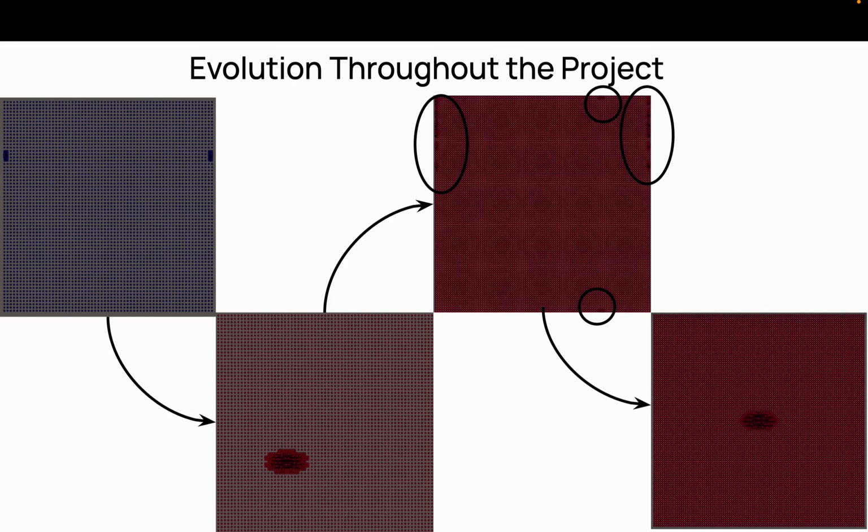At some point, when the precipitate was showing up in its hole though, it was round at the center and was showing up in random locations, as seen here in the second precipitate. After implementing the elastic energy properly though, this problem went away because the elastic energy implemented a more proper shape. Seeding helped control the location as well. So this is when elastic energy and seeding were done, the last precipitate shown here, but there was still no eigenstrain.